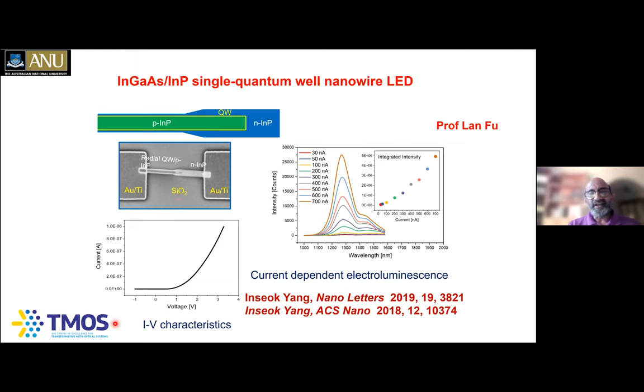He measures the IV characteristics, the current-voltage characteristics, and you can see nice diode-like behavior. That's what you would expect: with forward bias, higher current; with reverse bias, you end up having very low current. That's diode behavior. Then we inject more and more current and look at the light emission from these structures. You can see that the more current is injected, the higher the amount of light coming out. You also see two emission peaks.